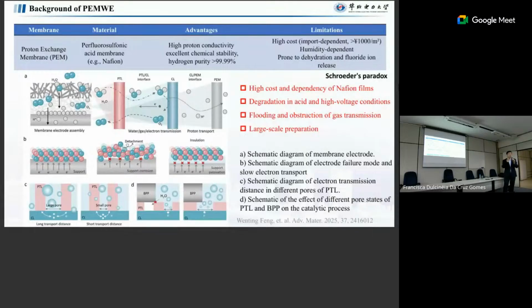We use a little bit of water or the vapor. But for the electrolyzers, we use liquid water. And the whole system is a bit different because the liquid water is a continuous phase, and the bubbles are a dispersed phase. Because of this, we have heard of Schroeder's paradox. That means normally we believe that when the relative humidity equals 1, we have the same swelling rate as the liquid water. Normally from thermodynamics it's the same.